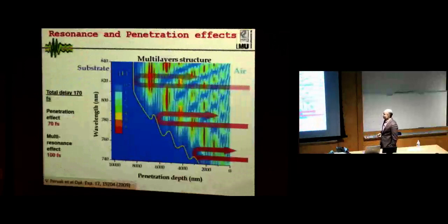But actually, the modern mirrors use, as I told in the previous slide, a combination of both effects. And here is an example of real mirrors. What we see on the figure, here we have a substrate. On the substrate, we deposit our multilayer structure. Here, just many different layers. From this side is coming our light, and for our convenience, I split the different wavelengths specially so that we can see the difference. Here we have 820 nanometers, and here we have 740 nanometers.